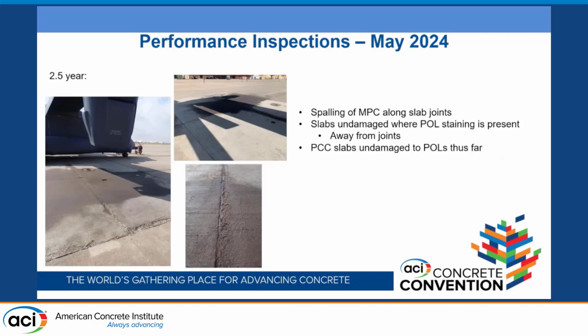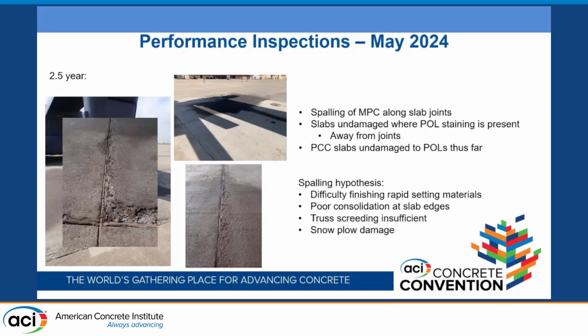So here's the 2.5-year inspections, and the big story is the spalling of MPC along slab joints. So there's your MPC slab joints. This one's pretty bad here. However, the slabs were undamaged where they were stained. So it was a joint issue. It wasn't a POL issue. And so the spalling hypothesis is difficulty finishing due to rapid setting, poor consolidation of the slab edges, truss screeding. Maybe we didn't do a good enough job with the truss screed, getting it level with the existing concrete, and it could also be snowplow damage if we didn't get it leveled well enough.